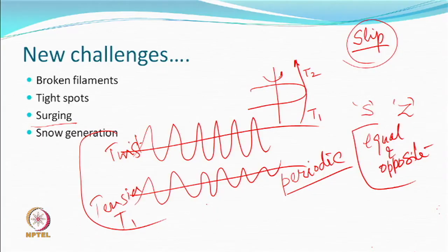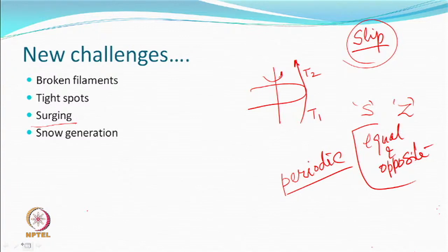Snow generation. So, this is a problem which obviously is again very, very specific to this process. Snow obviously is not the snow that we are talking about. There is abrasion. When there is a slip, there is abrasion. And which is the softer material? The yarn. Even softer than this is the surface which may have